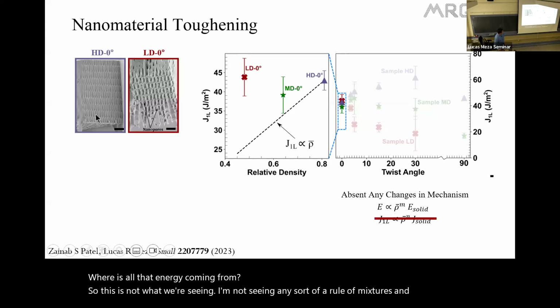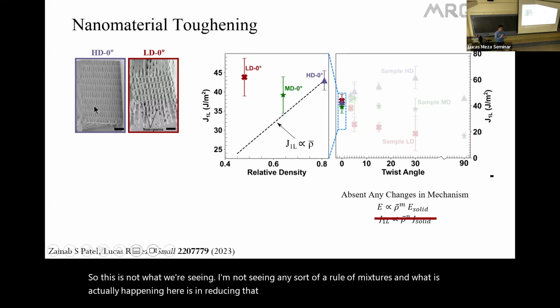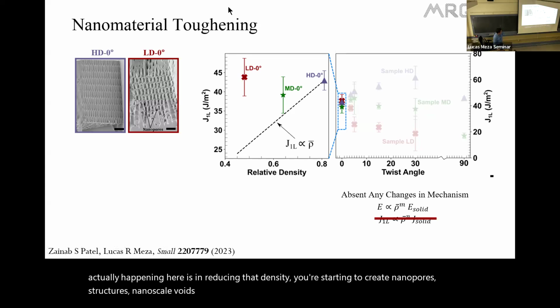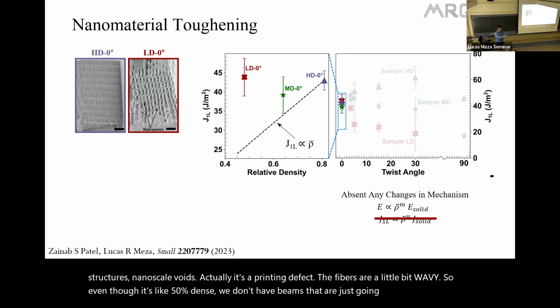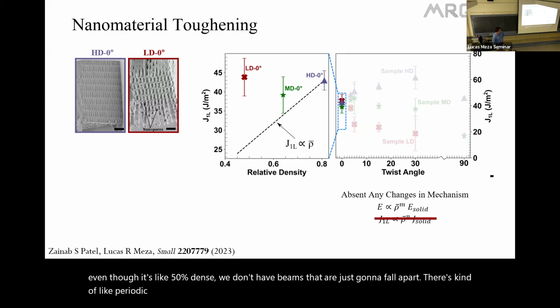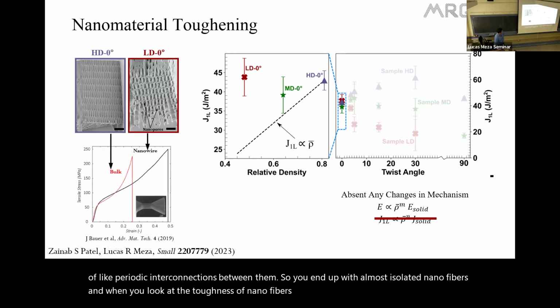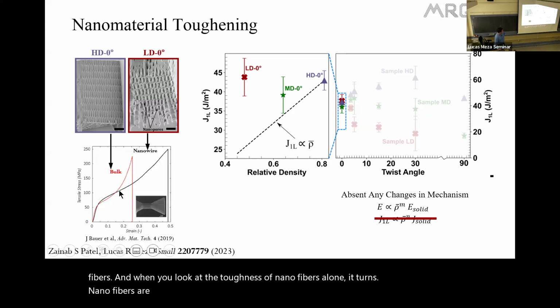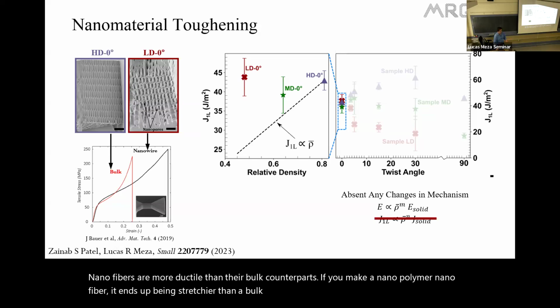And what is actually happening here is in reducing that density, you're starting to create nanoporous structures, nanoscaled voids. Actually, it's a printing defect, the fibers are a little bit wavy. So even though it's like 50% dense, we don't have beams that are just going to fall apart. There's periodic interconnections between them. So you end up with almost isolated nanofibers. And when you look at the toughness of nanofibers alone, it turns out nanofibers are more ductile than their bulk counterparts. If you make a polymer nanofiber, it ends up being stretchier than a bulk material would be.